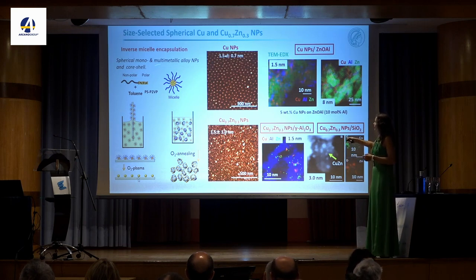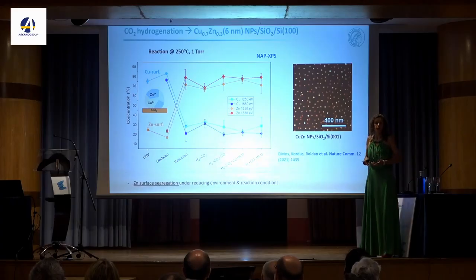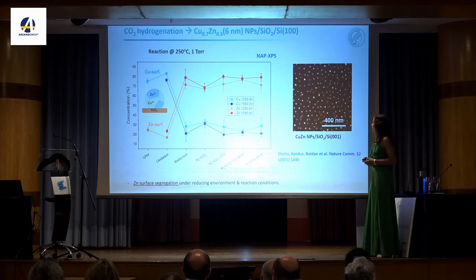So you can make the same particle size, but one could be pure copper, and the other one could have copper and zinc inside this micellar reactor. And so we started looking at what happens with the composition of this catalyst under reaction conditions, and we started with what we could do with the spectroscopy, first with near ambient pressure XPS.